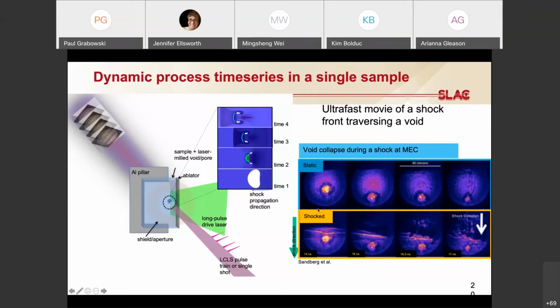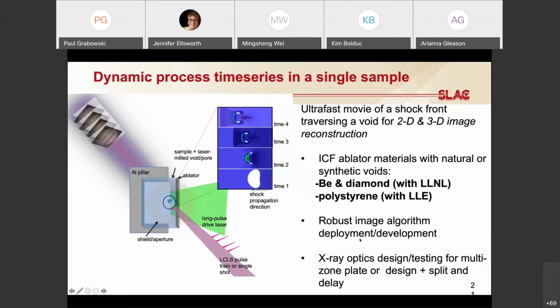And the idea that we're pursuing is shown here on the left as a schematic. So we have our sample with our synthetic void, and we want to take advantage, or have taken advantage, of the LCLS pulse train and probe 4 time slices in a single sample once we've compressed with the long pulse laser. So we get 4 snapshots, and then from analysis of these, reconstruct a 2-dimensional density distribution. Okay, materials matter, like I said.